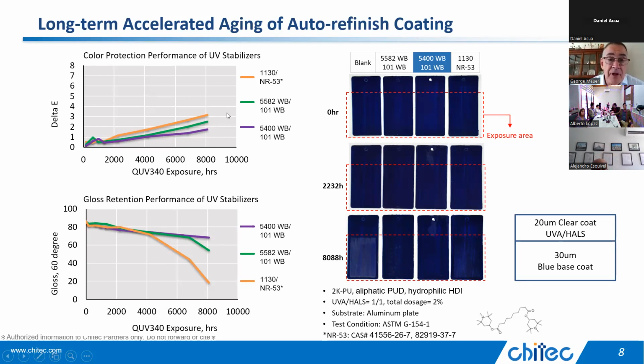And you can see how the 1130 over time, here it is a color test. The color's changing more with the 1130. And here's the gloss retention. And you can see after about 4,000 hours, the 1130 starts to be weak. And the reason the 1130 is weak is it goes away. And there's several reasons why it can go away. It has an ether-ester linkage on the outside, which is not very stable. And it's already water compatible, so it can wash out.